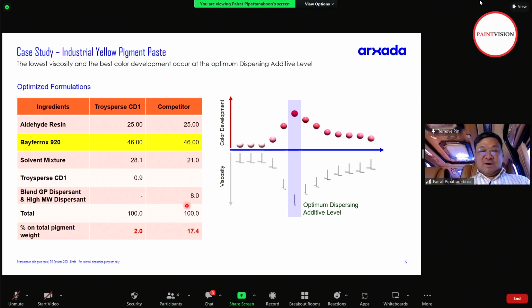The current formulation is the incumbent. The customer has to use two products, and they really use that in their real formulation, two types of hydroxyl carboxylate type dispersion. It used 17% of the dispersion on the pigment weight. CD1 is only 2% on the pigment weight.